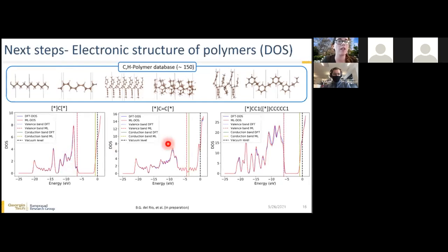We followed the same scheme as for the carbon database. We performed molecular dynamics of each chain at 300 Kelvin to obtain different types of configurations, and then some of them were left out for the test set. The others are for training, and within the training, we did a splitting between the actual training and the validation. And the performance, whenever I show it, is for the test set, so it's totally unseen configurations. Here I'm also showing the valence band and the conduction band, and even when they're very different, we also obtain good results. There are some modifications with respect to the carbon work on the graphene-derived allotropes, but in essence it's the same.